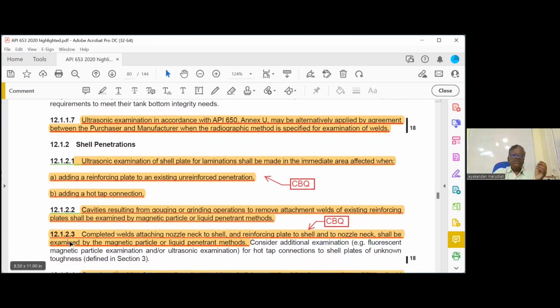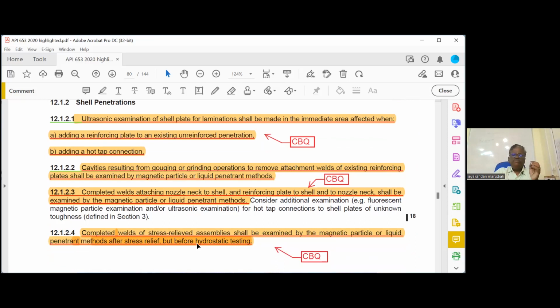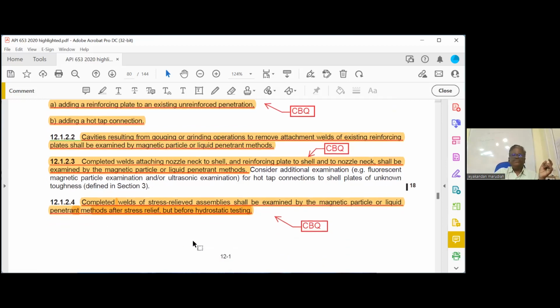Then highlight 12.1.2.1, 2, 3. Completed welds attaching nozzle neck to shell and reinforcing plate to shell shall be examined by MT or PT. So any fillet weld, generally we will do MT or PT. Then PWHT. If you are doing any PWHT, after PWHT, MT is mandatory. Completed welds of stress relief assembly shall be examined by magnetic particle or liquid penetrant after stress relief before hydro test.